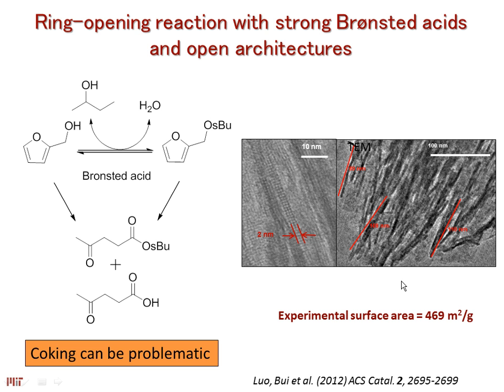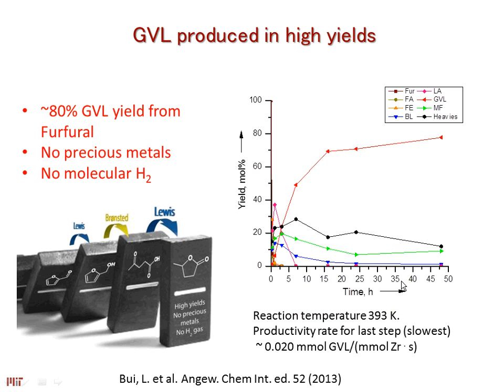So with that, we're able to use both catalysts simultaneously and either in flow mode, or in this case I'm showing the batch reaction data. We're able to obtain GVL starting from furfural with very high yields without using these precious metals or molecular hydrogen. And we actually show that even starting from the carbohydrates, from hemicellulose or xylose, you can still obtain very high yields, not as high as 80%, but you're in the low 70s in that respect.